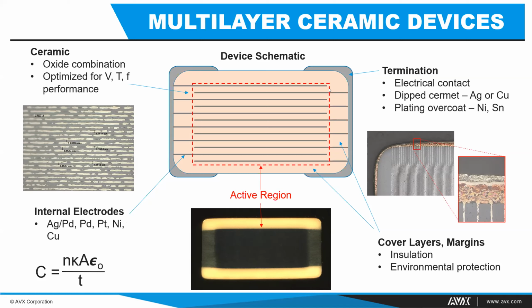In order to make a connection between these, the ceramic device and the outside world, some type of termination is used. This is where we make that electrical contact. It usually consists of a dipped Cermet type product. Often that is based on either silver in the case of precious metal electrodes, or copper in the case of base metal materials. Often both of those materials as the base would require some sort of plating overcoat. So we use a combination of nickel and tin in most devices, and you can see the kind of combination.